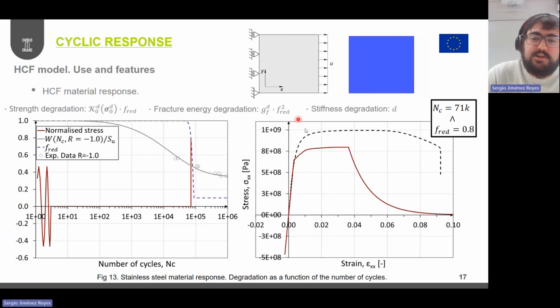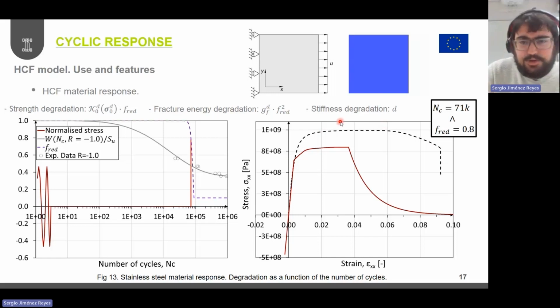So basically what I'm doing here, first of all, is applying some amount of cycles in that element, and then apply a tensile test on that element and see what is the response of the material. So basically, we have here the monotonic response of the material as reference, and then what you can observe here is the response, this tensile response of the material.